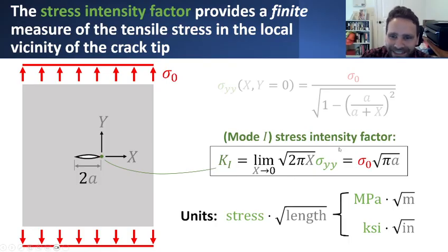But the mode 1 stress intensity factor is really a specialized way of trying to measure how big the stresses are in the local vicinity of the crack tip. As I said, we can't measure what the stress is right at the crack tip because it's going to be infinite. So there's really no good way to compare how big this infinite value of stress in the crack tip vicinity is versus another infinite value. It just doesn't make sense. We can't compare infinity to infinity. But we can compare a relative intensity measure that applies to the stress and which also involves some dependence on the geometry of this plate structure. And we call this, again, the stress intensity factor.